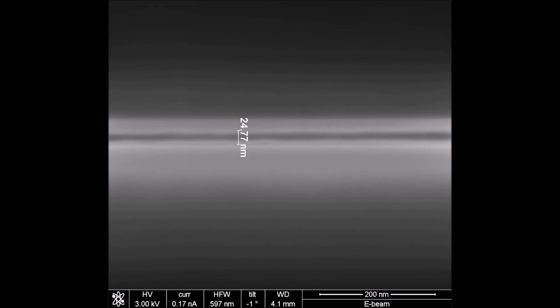So one of the things that happened with this lamella when I did the first 5 keV step, because it was a little bit too aggressive, because I didn't wait for the image instability to calm down, was I ended up with a little bit of a discontinuity in the cross-section face as a result of that step. So when I view the lamella edge on, you can see I have that distinct dark line in the middle, which would be the top of the lamella, but you can see I have a little bit more material on the upper side as opposed to the bottom side. And again, the presence of any of those discontinuities may not even be important. It's not important in this case because we're interested in imaging the very near surface region of the specimen.